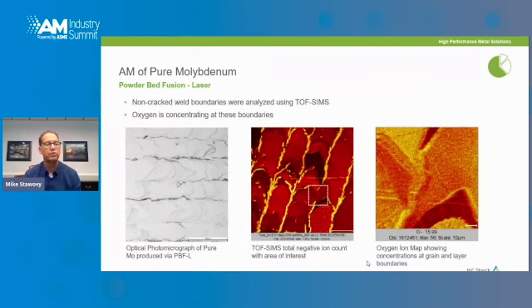Here we show this same pure molybdenum microstructure, and we've done some TOF-SIMS analysis, which is a technique to look at the chemistry at these cell boundaries. And we've zoomed in on some of these cell boundaries and see that there are some high concentrations of oxygen that is occurring at these cell boundaries.